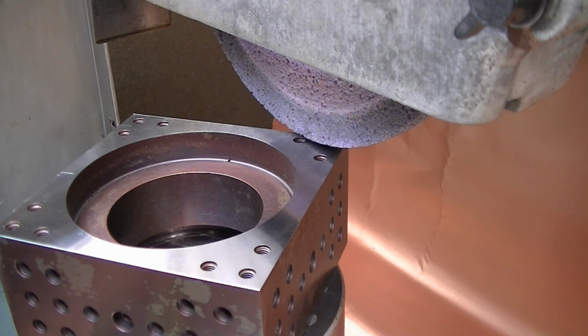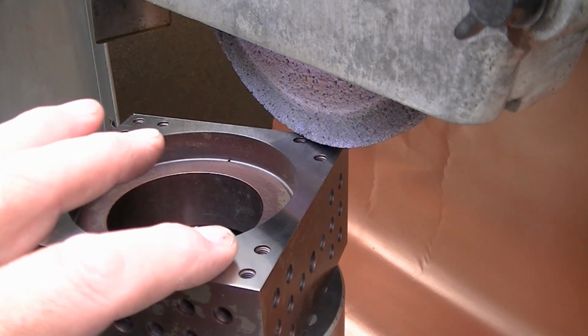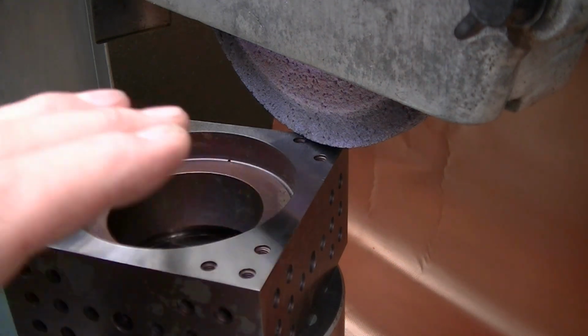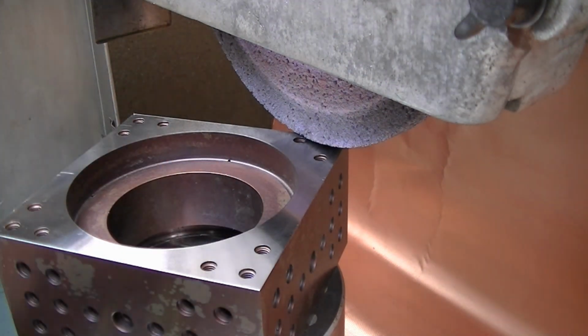It pays to use much finer grit wheels that are dressed properly, meaning open, like a 150 grit wheel or a 220 grit wheel sometimes, to get the finish you're after without dressing the wheel in a glazed condition. That sharp wheel is very important for this high precision work, so that it can cut freely and the amount of pressure needed to initiate a cut is very low.